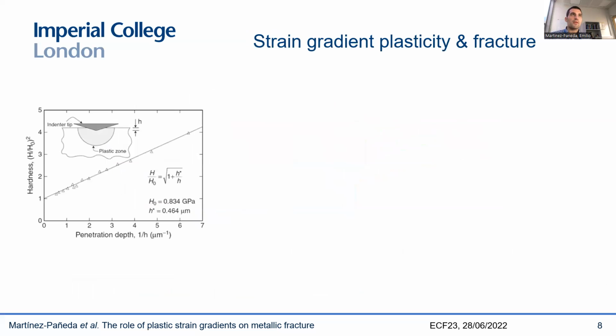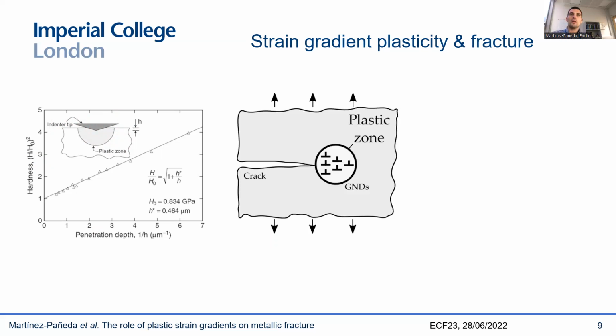And I should emphasize one thing here. When I'm talking about fracture and gradient effects and size effects, I'm not anymore talking about small samples, very thin wires. I'm talking about large samples which have a small plastic zone adjacent to the crack tip. And this is similar to what you see in indentation, right? So you have an indenter here, you may be indenting a very large sample, but you get size effects associated to the fact that you have a small plastic zone near your indenter tip. So the size effects are related to the size of the plastic zone, not necessarily the size of the sample.